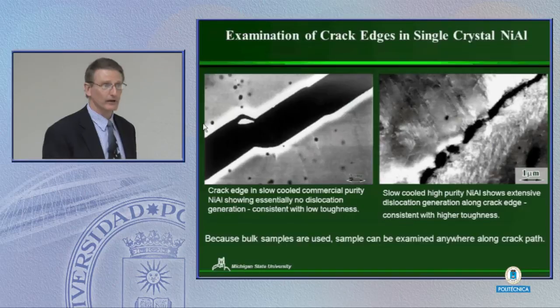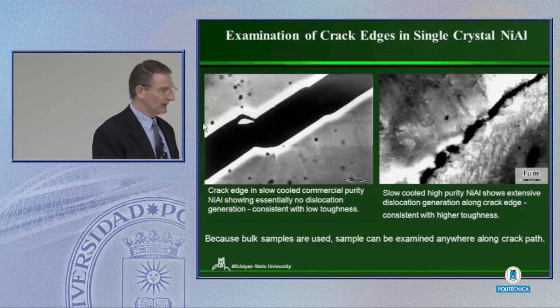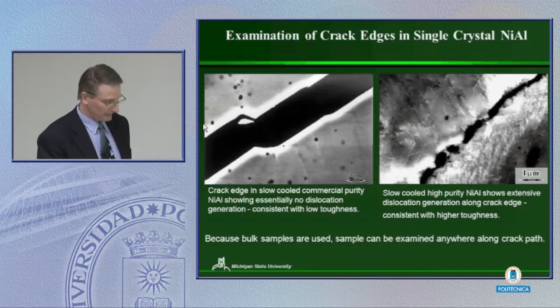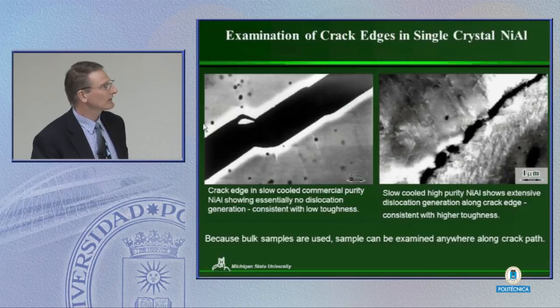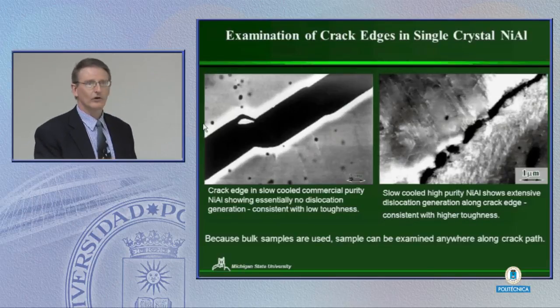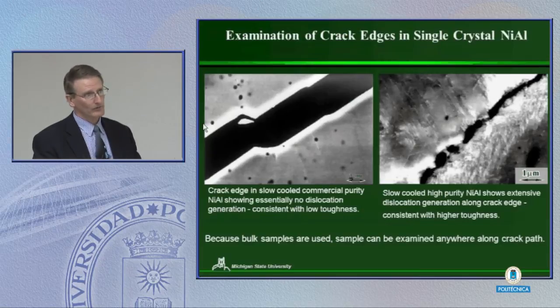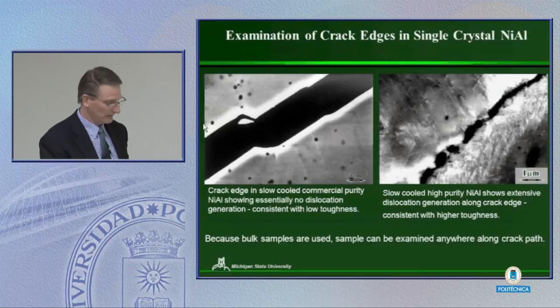Now there's maybe some relaxation after the load is released and everything, but what we've seen in general is the crack tips, or I should say the plastic zone, ends up being much larger when the crack actually arrests. So it runs out there, and when it slows down, we seem to get a little bit larger plastic field.